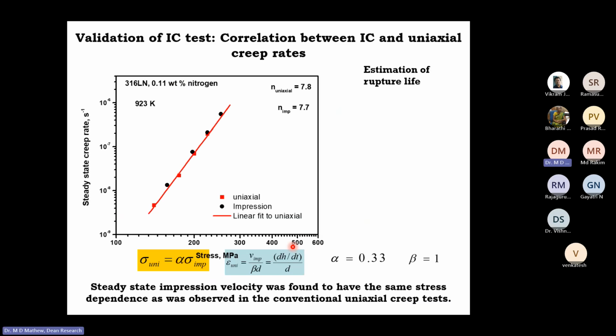So the next question is, how do we correlate the impression creep data with the data from standard conventional creep tests? And I already explained the conversion of the mean pressure to uniaxial stress and the impression velocity to strain rate with constants alpha and beta. So this is the correlation. On the y-axis, you have the steady state creep rate. I'm sorry, this is again a log-log plot of steady state creep rate versus stress.